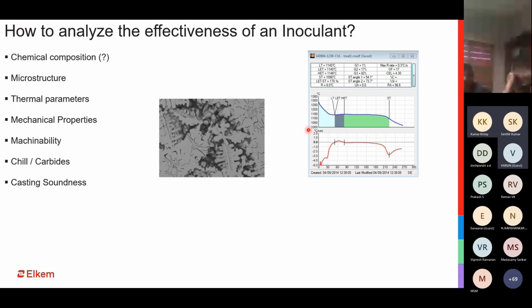Then when you are able to get the desired graphite precipitation, it would mean that you will have much better control on your carbides and the chilling tendency in the casting. And when you have good thermal properties, good mechanical properties, and a good microstructure, I'm pretty sure that we will also have much better casting soundness. When I say casting soundness, I mean the casting which does not have any voids, any porosities, or any shrinkage, something like what you see here.